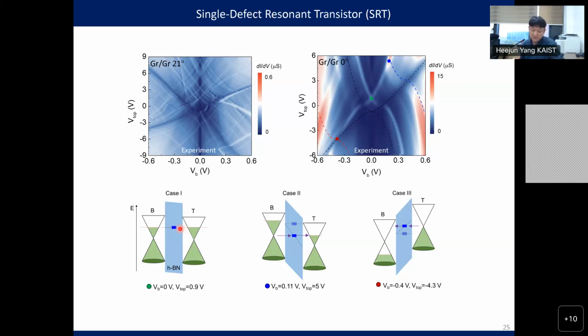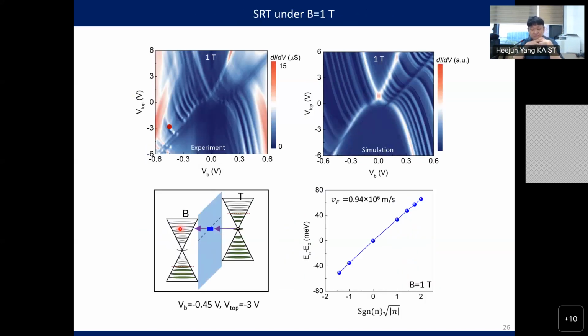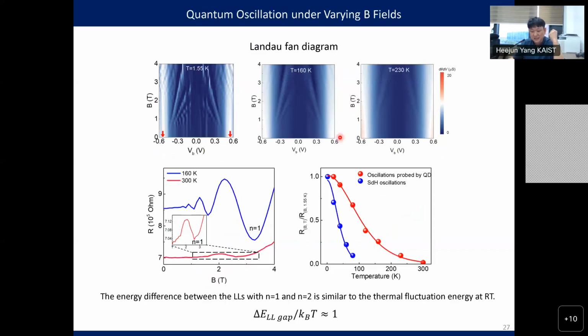Anyway, we have this phenomenon, and then the result is, of course, if we apply a vertical magnetic field, we have Landau levels, and this is the quantum Hall effect. And then the quantum Hall effect, of course, with this Dirac velocity, we measured it. And here, the quantum Hall effect could be measured at 300 Kelvin. I like this room temperature quantum stuff. And the reason is here, as I said, we have quite few defects. Few defects with a certain period for matching the K momentum of the electrons in the graphene. We have a very little chance.